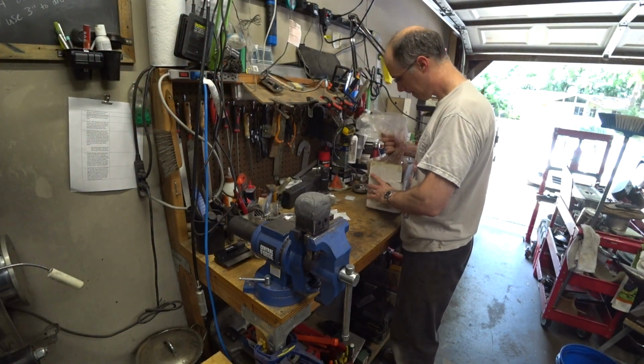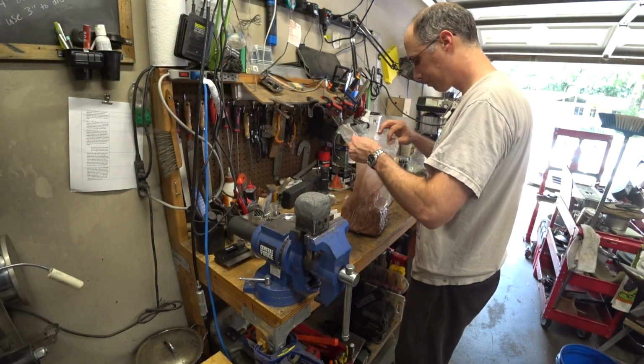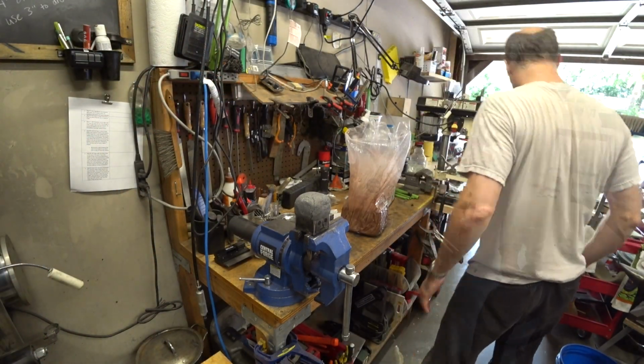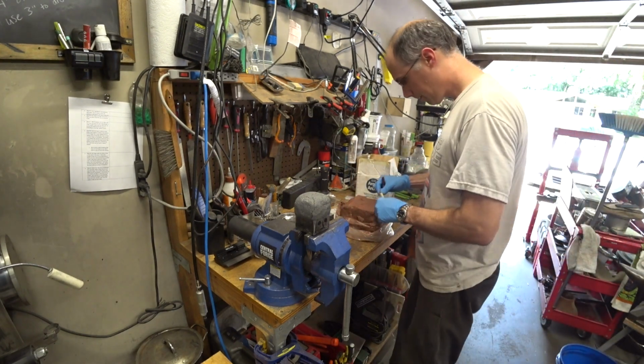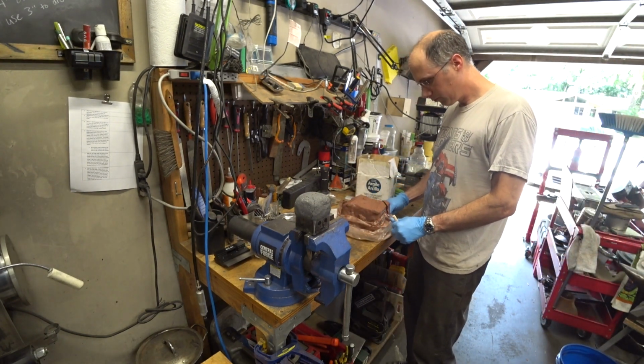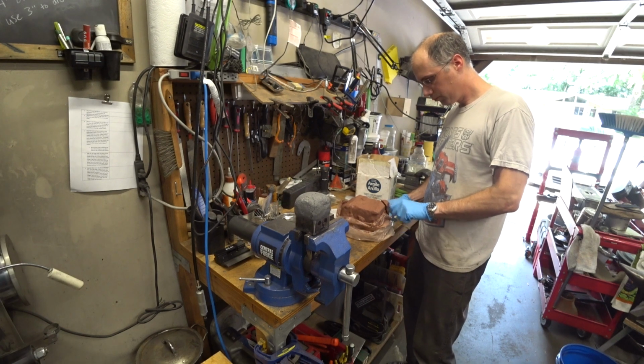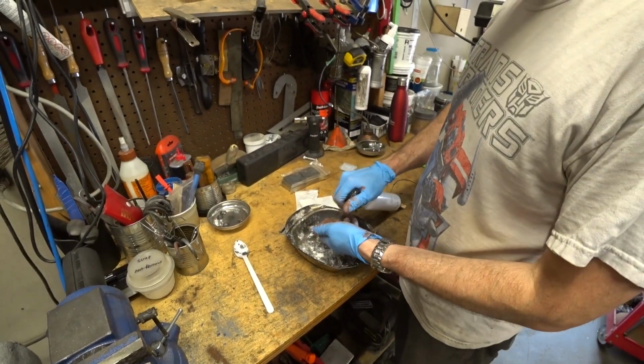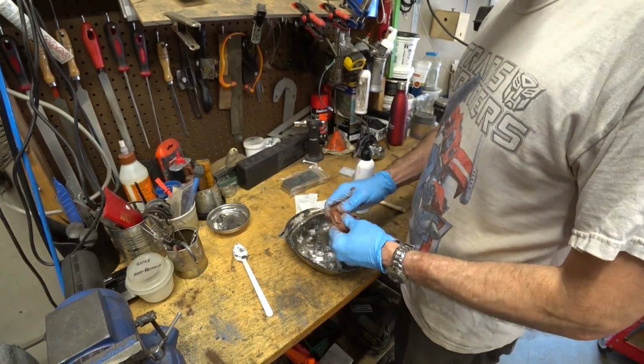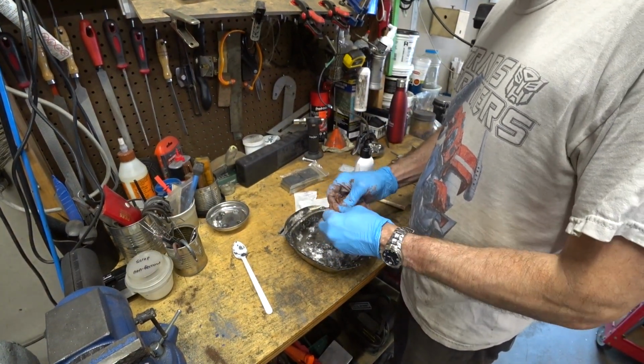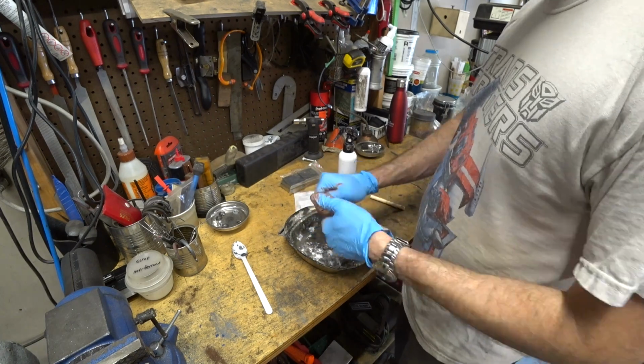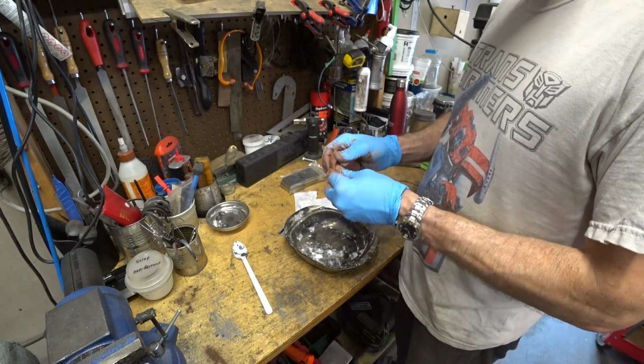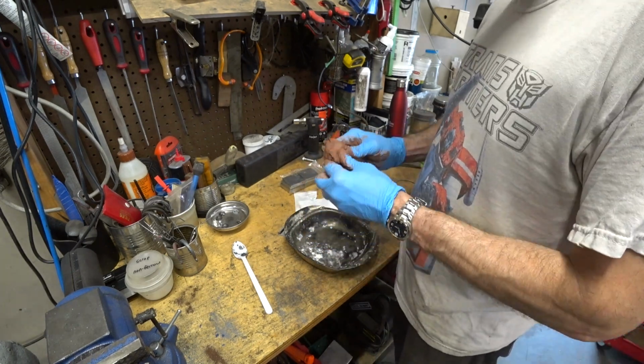Now that the compound is completely hard and dry, it's time to coat it with some clay. The clay will form a hard protective coating that will trap the carbon monoxide inside as the charcoal burns. It's the carbon monoxide that actually penetrates the metal and produces the case. I already happen to have some terracotta clay from another project, and so that's what I'm going to use to coat the outside. It's pretty dry, so I need to moisten it and then massage it in order to soften it up.